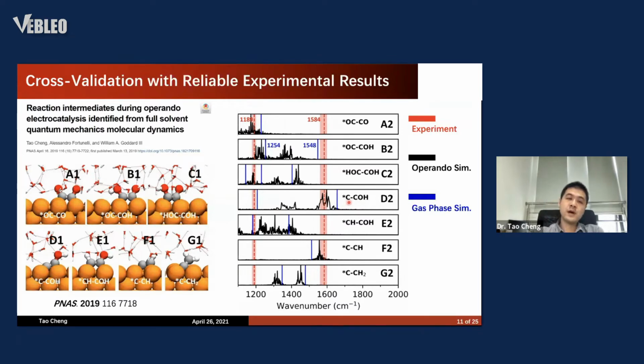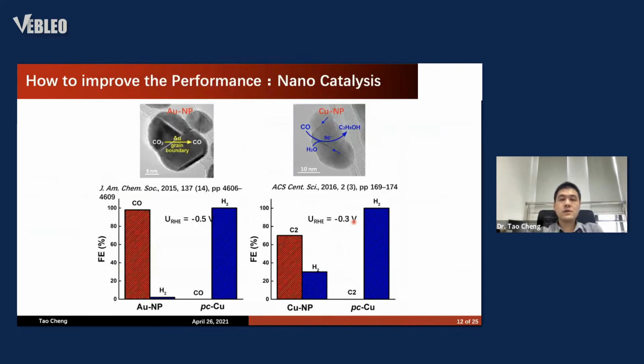So another thing I want to draw your attention to is that if you use the traditional gas phase simulations, you end up with this blue line. Then if you compare the blue one and the black one from our simulation, you can see that it's very different. And none of these can explain the experimental result. So this means that if you want accurate predictions, you need to develop methods that are accurate. So now, because we fully understand the reaction mechanism, what we are trying to do now is improve the performance.